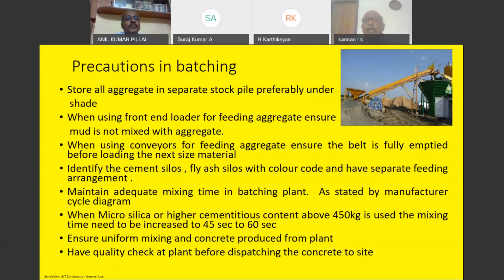When using conveyors for feeding, as I said, fully empty them before loading, and identify cement silos and fly ash silos with a color code. Basically, today we are using different cements and different mineral additives. Some project sites are handling sulfate resistant cement and OPC. Some are handling OPC and PPC. Some are handling OPC, PPC, and fly ash and slag separately, depending upon the usage. So unless you identify the silo with the right color coding system, your feeding can go wrong. The wrong material can go into a wrong silo.